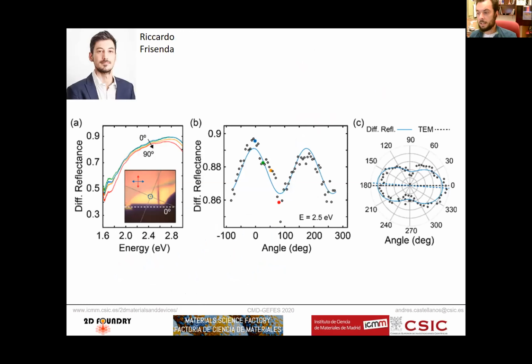And interestingly, this kind of spatially varying strain induces a lot of anisotropies in the system that were not present in the naive model where you place the hexagonal, tetragonal, hexagonal, tetragonal layers. In the nice cartoon where you have just these layers on top of each other without interaction, these systems should not have any strong optical or electrical anisotropy. But once they start to interact and develop this strain that varies spatially, then the system develops this